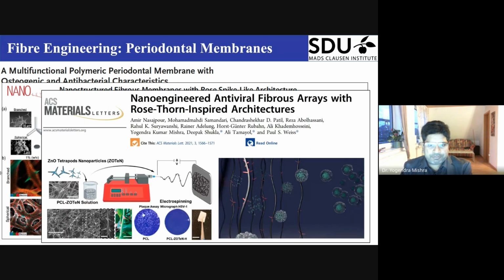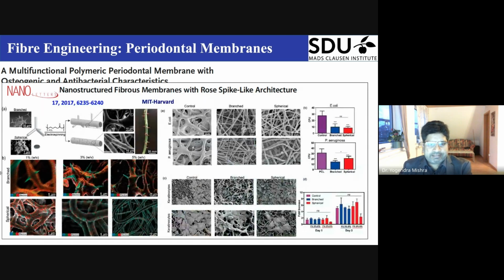And this allowed them, basically they got motivated, and then we put in the tetrapods, and we were able to design these rose spike-like structures. These spikes are zinc oxide spikes, and this is a PCL fiber. We demonstrated this. PCL is a polymer fiber, a biodegradable fiber, which is used to stitch wounds. We always have a question of reinfection after surgery.